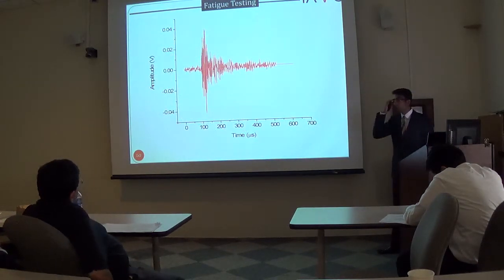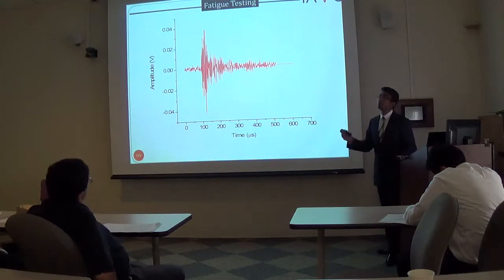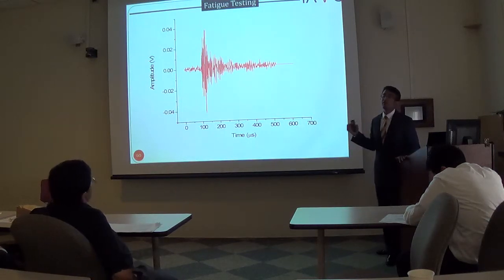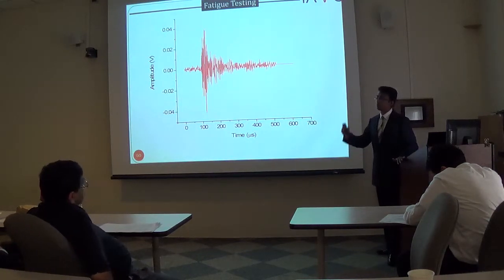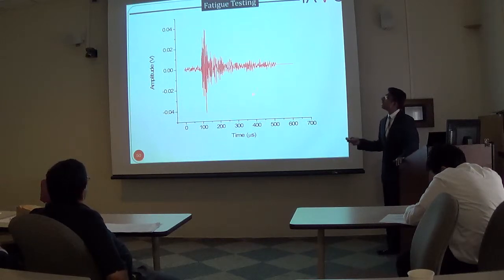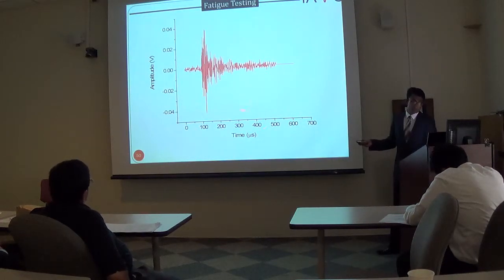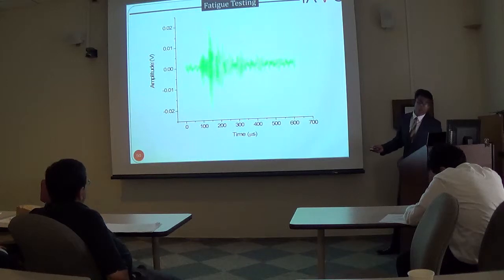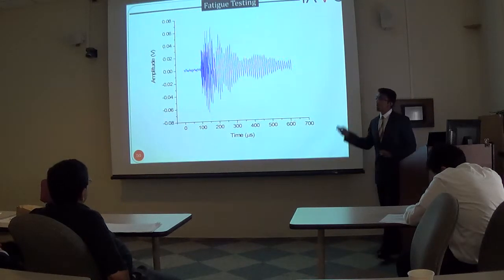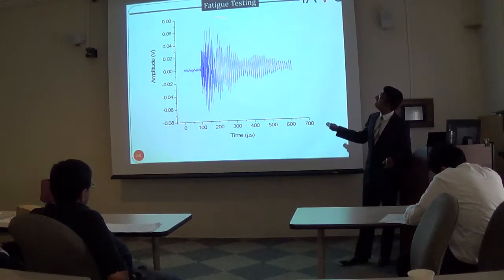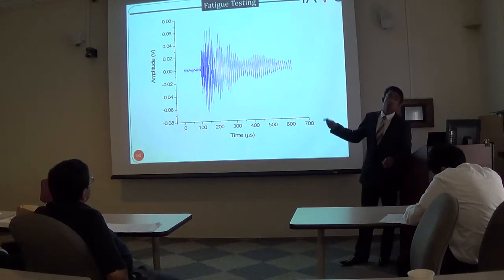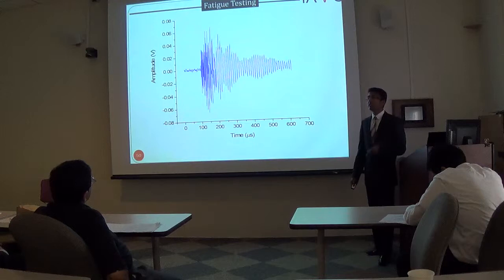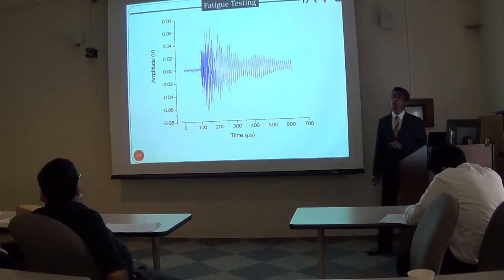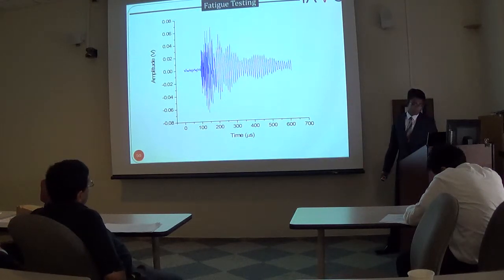Now, in order to understand what perhaps could be associated with debonding in terms of the classes, the AE waveforms that were representative of the different classes were extracted and analyzed. So the class 0 signals had a burst type emission like the one shown here, while the class 1 signals were seen to have AE signatures as shown here. But the class 2 signal was seen to have very similar AE waveform signatures to the ones that were extracted during the tensile test and during the location algorithms that were performed during fatigue testing of the material.